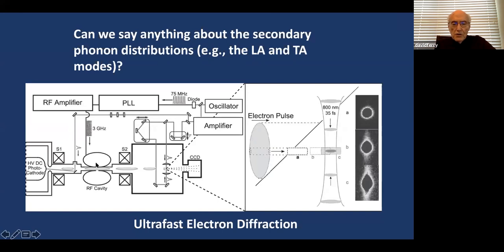This system here is what's called ultrafast electron diffraction. Sometimes you need a free electron laser to make all this work, but that gives you ultrafast X-ray diffraction as well. But let me explain this to you. This is a laser oscillator, and it's a mode locked laser. So it pulses at 75 megahertz. You get a laser pulse out 75 million times per second. And you detect it, and you send the 75 megahertz pulse signal into a phase lock loop.